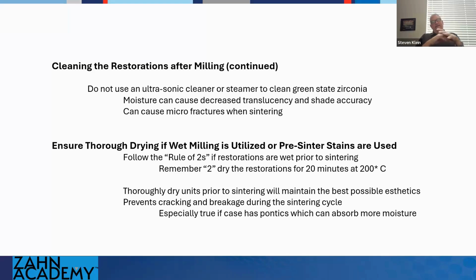Now, the flip side of that coin is that some machines are wet milling machines, and so you have no choice but for it to be wet. Some laboratories will utilize wet milling just to keep the dust down as well. I don't recommend it. It's better to get dust controlling systems as opposed to sacrificing the aesthetics of your product. That's your calling card. That's your main business, those particular zirconia crowns. So you want to make sure that you're delivering the best possible product to the doctor that you can, and getting moisture and wetness on them is not the way to do it.